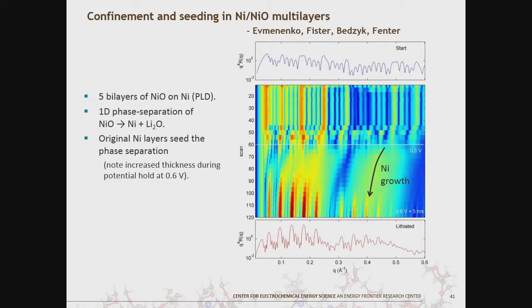I guess you can get a sense for how uniform the layers are during this discharging. That suggests that the lithium is diffusing as a solid state diffusion through all the layers. Yes, the lithium is going through these active materials, but it's getting through the metal as well as the active materials, and so there is some kinetic limitations. The fact that the Bragg peaks are disappearing here indicates that it's not actually completely uniform.